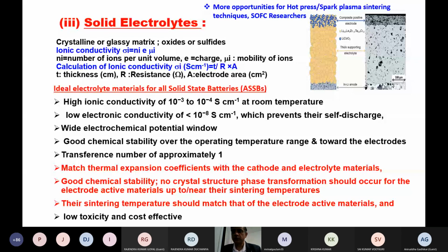You have to make sure the material is more mechanically stable, and we need good conductivity, which means particle-to-particle contact is needed. These are the various approaches people are taking. It is very important that the thermal expansion coefficient matches the cathode and anode, since we are sintering at high temperature, for example spark plasma sintering, simple hot pressing, or pellet pressing with re-sintering in the furnace. The major issue is how the interface is going to react with the material.